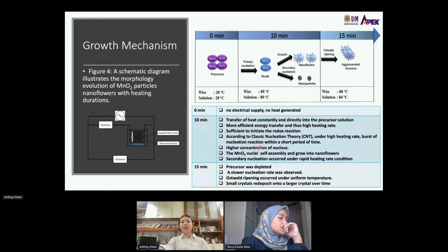According to classical nucleation theory, under a high heating rate, a burst of nucleation will occur in a short period of time. Therefore, we will have a lot of MnO2 nuclei. These nuclei will self-assemble and grow into nanoflowers. Besides, under a high rapid heating rate condition, secondary nucleation will occur. Therefore, we observe some nanoparticles deposited on the nanoflowers.